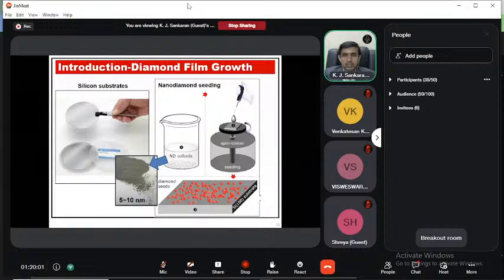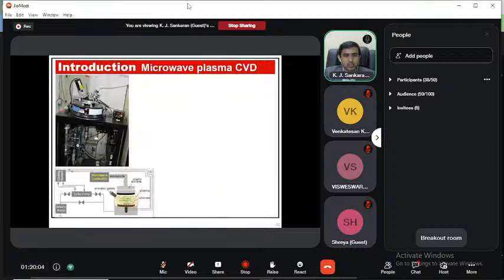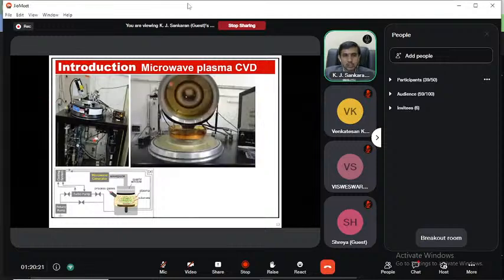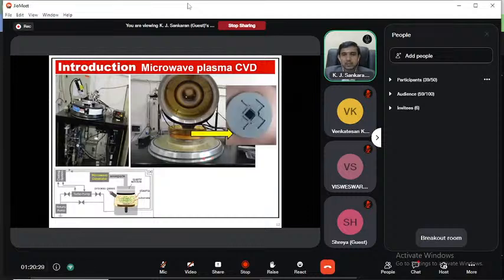Then these silicon substrates are placed in the microwave plasma CVD. This is available at Hasselt University, Belgium, and this is the schematic diagram of the microwave plasma CVD. This is the chamber, and these are the control panels for the microwave, the flow of gases, and the control of the pressure. Once you open the chamber, it looks like this, and this is the sample stage, which is covered by the quartz ring, and this is the chuck where we keep the nucleated silicon substrate. So this silicon substrate will be placed inside this chamber. Then the chamber will be